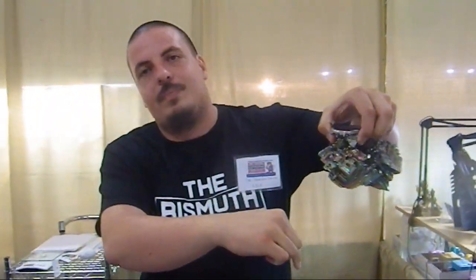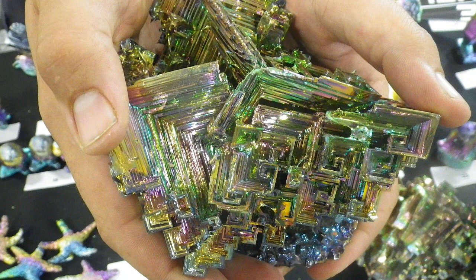We give it a seeding point and it actually supercools, like water does — it'll go below the temperature it's supposed to be solid at. Then we give it a seeding point and the crystals grow. What kind of temperatures are we talking here? Just 550 Fahrenheit, 220 Celsius. It's incredibly hard to get the crystals to grow without forming crystals in other places, so to get large crystals, you can only have them seed in one space.